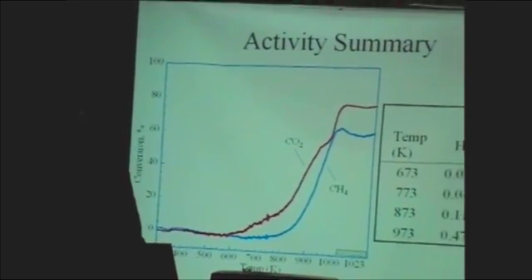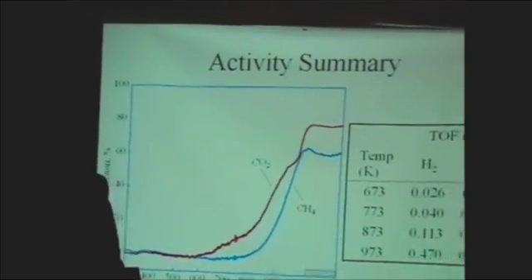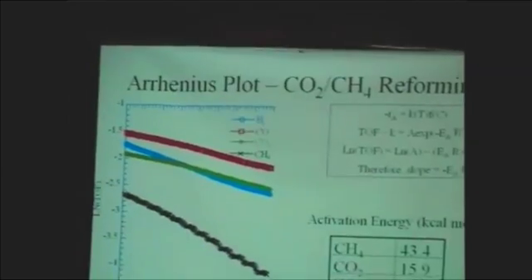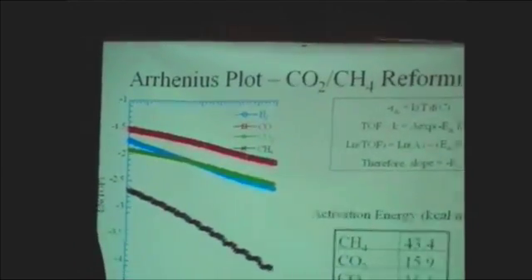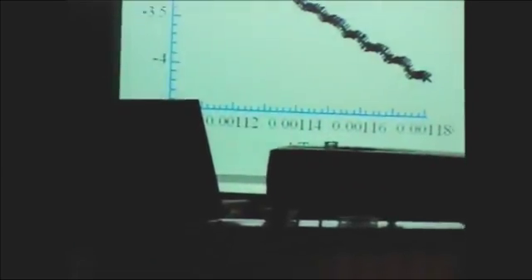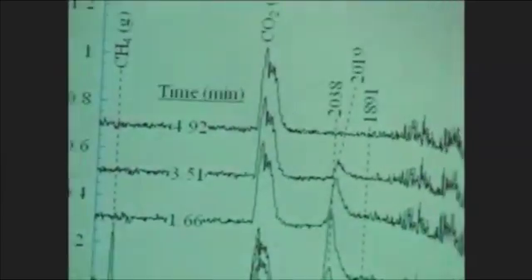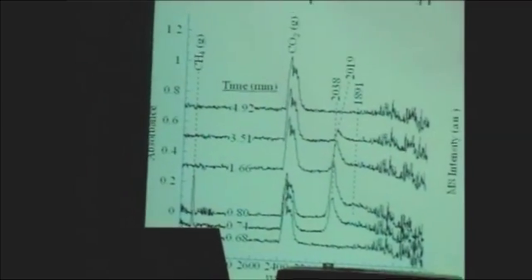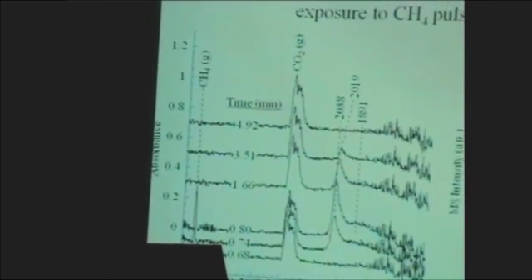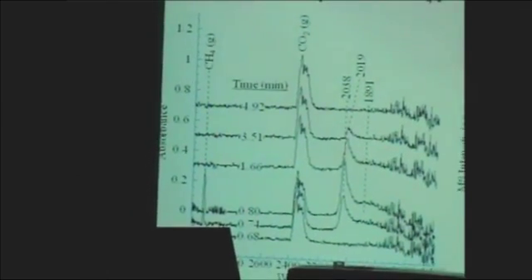So the first thing we did here is run this reaction over the catalyst and determine the activation energy, and compare the activation energy with the literature value to make sure our catalyst is active. And after that, we start to play with the tracing technique to try to figure out how this reaction takes place on the catalyst surface.